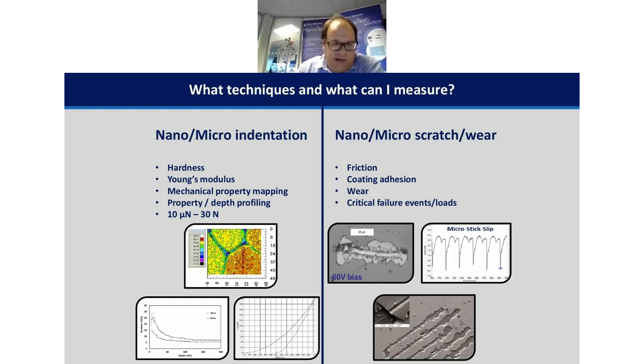You can see here some mechanical property profiles for coated samples, 40 nanometer and 80 nanometer hard coatings on glass substrates. Indentation is used for that, and we can also work at larger scales, so micro indentation up to 30 newtons for looking at bulk properties of materials as well. So we're not just limited to the very small scale end of hardness testing.